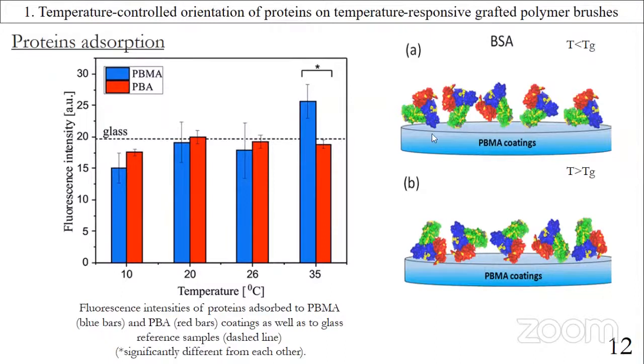BSA adsorbed to PBMA coatings below glass transition temperature adopts such an orientation that albumin 1 and 2 are exposed out of the surface, whereas for temperature above transition, albumin 3 is exposed. The control of the orientation of proteins plays an important role in obtaining good steric accessibility of active binding sites and increasing stability.